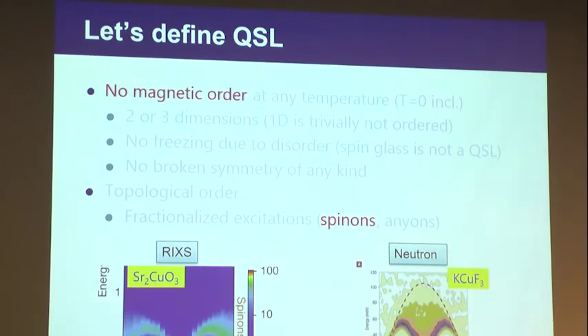And spinons can be measured both using inelastic neutron scattering as well as resonant inelastic X-ray scattering. This work was done at the Swiss Light Source on strontium copper oxide, and the neutron scattering work was done on potassium copper fluoride. Unfortunately, both of these works were done on a 1D spin chain, a one-dimensional material, which is actually ruled out in this quest for quantum spin liquid. But we do know how to measure and study quantum spinon excitations.